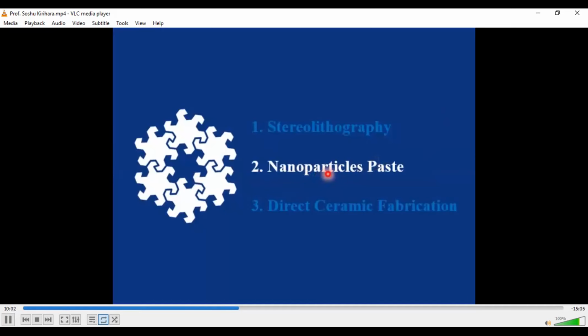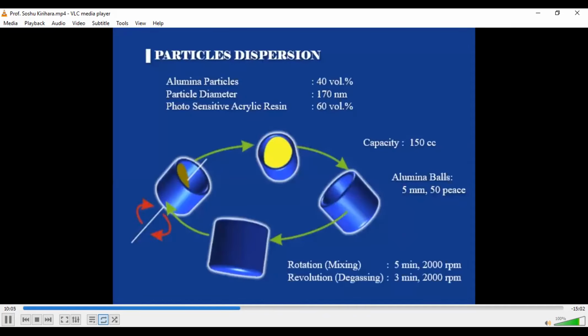The next process is a nanoparticle pasting process. We tried to increase the ceramics particle dispersion amount in the photosensitive resins. In this case, 40 volume% alumina particles with a particle diameter of 170 nanometers were dispersed into photosensitive acrylic resin by using a rotation and revolution mixing machine. Rotation means mixing like this, and revolution means mixing like this. The revolution is the degassing, and the rotation is the mixing of the solid particles in the liquid phase.